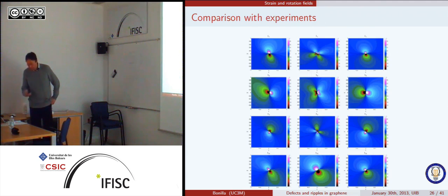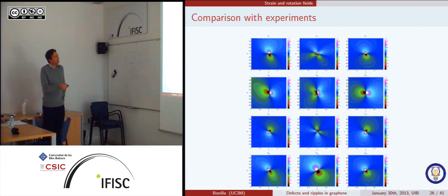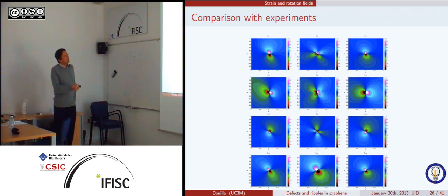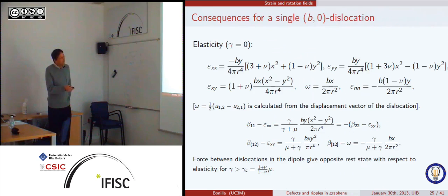So I'll show you first what happened. This is the experimental data. This is the predictions of linear elasticity. So you see that they are qualitatively quite different. And this is what we did with something that I'll show you in a minute.